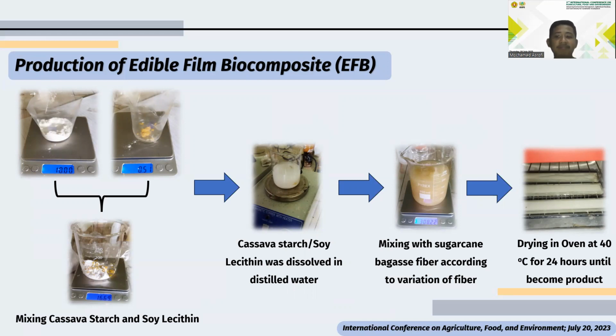After that, the biocomposite mixture was cast into a rectangular glass mold, like this, and dried in a drying oven at 40 degrees Celsius for 24 hours until it became a biocomposite or bioplastic product.